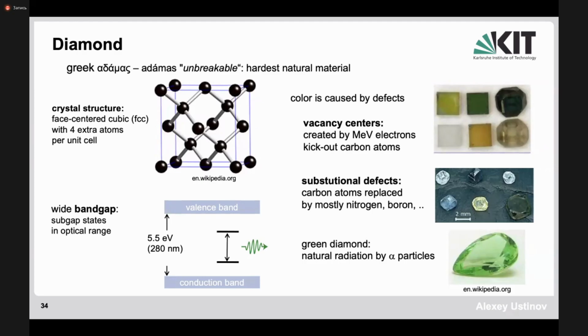So the crystal structure is a face-centered cubic structure, and you need to imagine that there are 4 atoms in the unit cell, and then you multiply this unit cell according to the symmetry of the face-centered cubic lattice. Now, the defects which occur in diamond make the material not fully transparent, or at least give it some color. And natural diamond, which is found in mines, can also have different colors. And this all depends on the type of impurities.